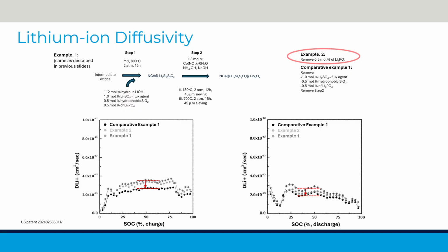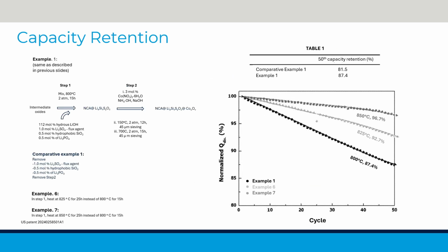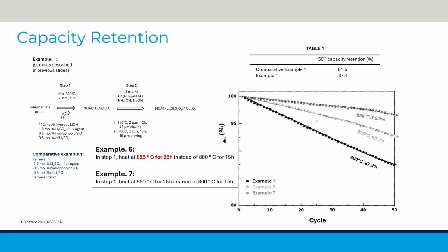It's because lithium phosphate serves as an ion-conducting but electron-insulating barrier that allows lithium-ion transfer. At the same time, it inhibits unwanted electron conduction and minimizes parasitic reactions that contribute to resistance buildup. In terms of capacity retention, coated particles behave significantly better than the uncoated comparative example. It seems that a slight increase in firing temperature with longer duration does produce particles with better stability.